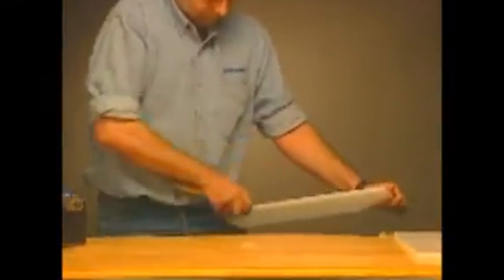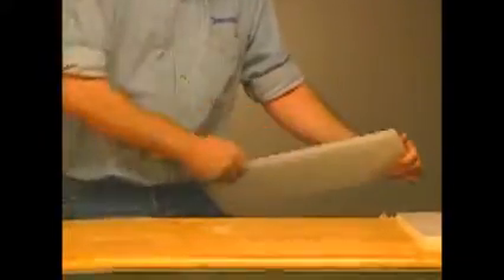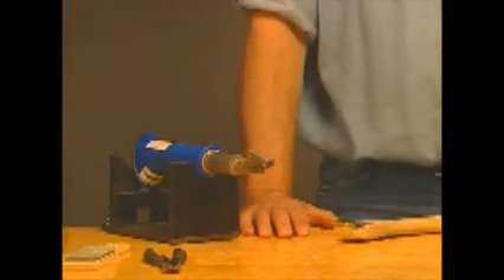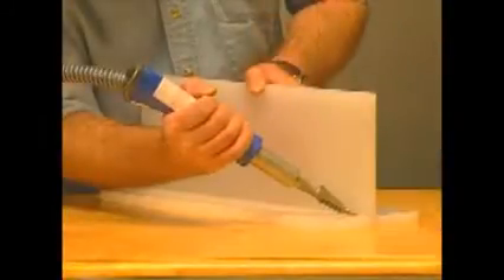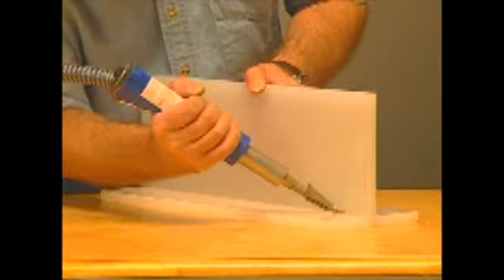Now scrape the edges of the material to provide a smooth fit. The first weld process is tacking. Flip the tacking tip to the front. Allow it to heat up for 30 seconds, and with slight pressure, move it along the area to be welded.